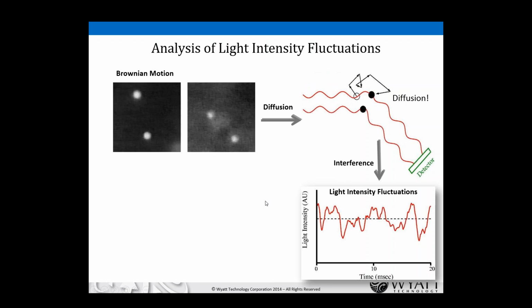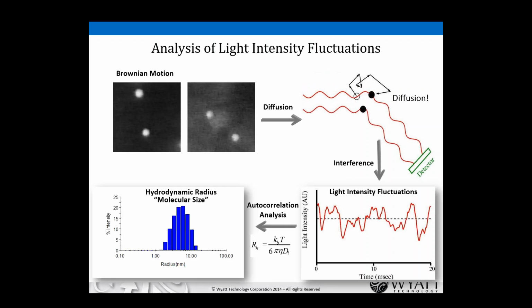So the time scale here for these relatively large particles, which we could actually take videos of, is milliseconds, but for smaller particles, for instance, monomeric proteins with their aggregates, you're actually looking at fluctuations on the time scale of microseconds. So we have fast detectors that pick up these fluctuations, and then we apply a mathematical algorithm called autocorrelation analysis, and what that does essentially is determine the spectrum of rates of diffusion. So dynamic light scattering is measuring from first principles the rates of diffusion.